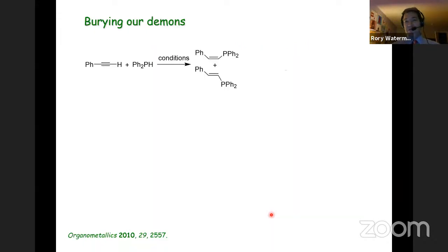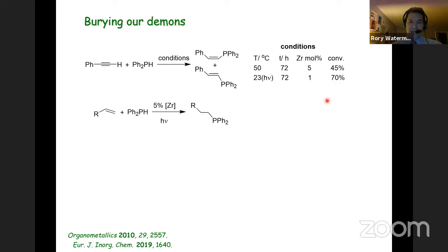And so the first thing along that path, of course, is to go back to the reaction that I showed you at the beginning for hydrophosphination, which was this hydrophosphination of terminal alkynes to give mixtures of vinyl phosphine products. In the original catalysis, it was elevated temperatures, long reaction times, and relatively high loadings. When we can irradiate at ambient temperature for the same time period at much lower loading, we can get better conversions. So we were feeling better about the reactivity that's possible, and it was nice to compare ourselves to what we could do. And those reactions then in general allow us to start to explore other substrates with the secondary phosphine substrates.